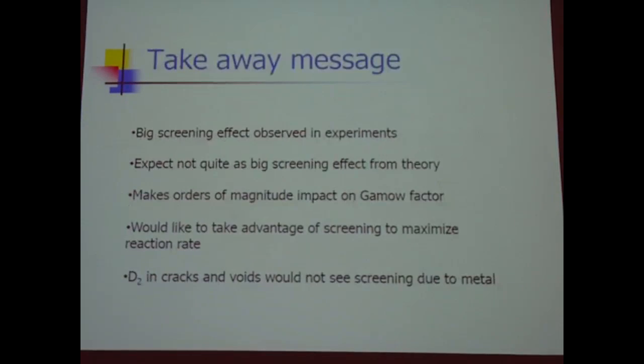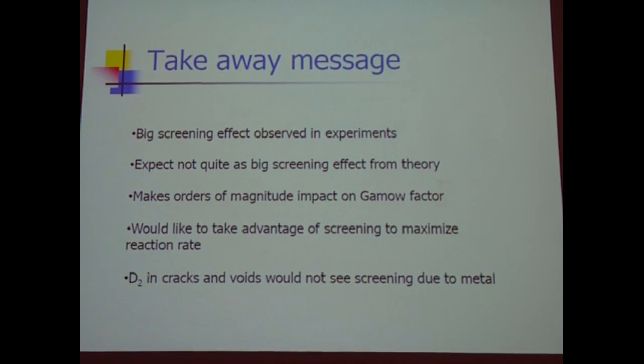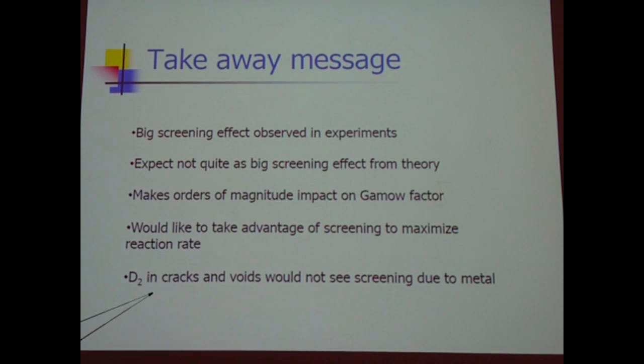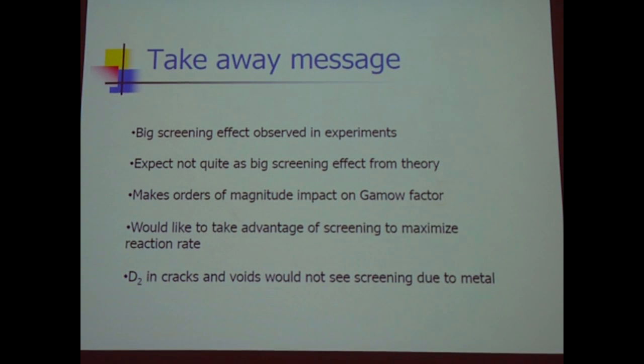Okay, so takeaway message. Big screening observed in experiments. Expect not quite as big screening from theory, but that's not really right. That's apples and oranges. Thomas Fermi gives lower screening for the static problem, but the beam problem is the dynamic problem. And for the dynamic problem, I haven't seen the papers yet where that's been analyzed in detail with modern models. It makes orders of magnitude impact on Gamow factor. We want to take advantage of maximum screening to get maximum reaction rate. D2 in cracks and voids wouldn't see it, but D2 in a monovacancy should see the screening because we're getting the D2 molecular form where there's some non-trivial amount of electron density, and we've got nearby outer orbitals in metal. Catch my breath. Questions? Comments?